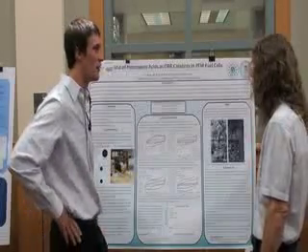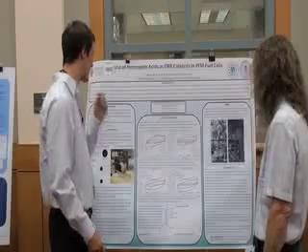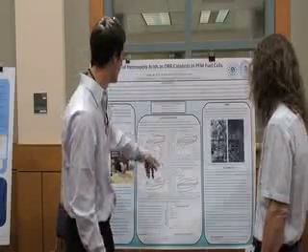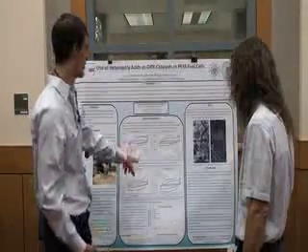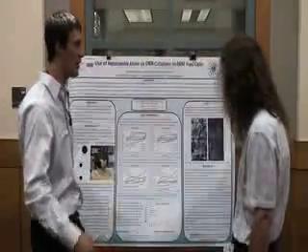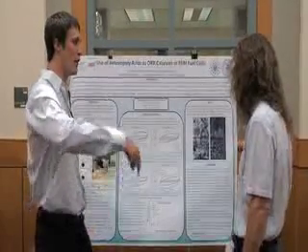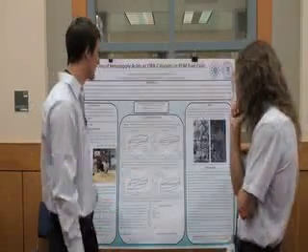I guess the whole thing is hugely different depending on pH, right? Oh, yeah. And that's why we wanted pH 2. And so this potential is versus silver chloride, and this is a range in which a fuel cell would operate. And that's the major concern, the startup and shutdown, where you have those really high potentials, and that's where platinum dissolution comes in.